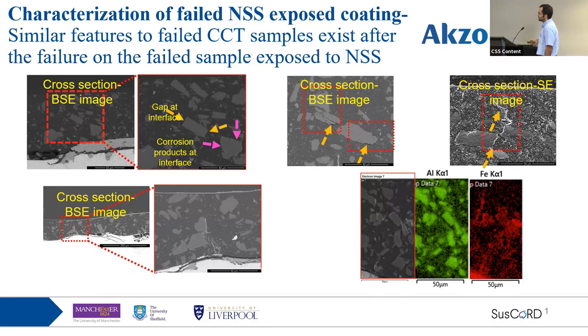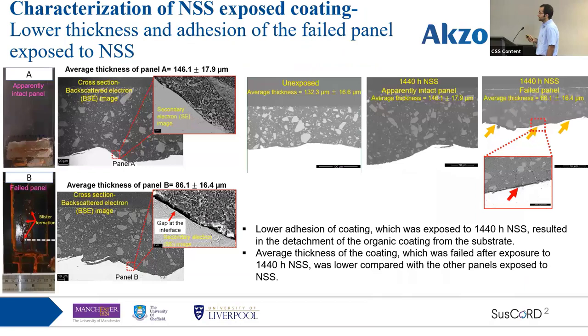But when we looked at the unexposed, apparently intact areas, we couldn't see any crack formations on the samples that were exposed to the neutral salt spray test. So in order to find out why this panel has failed, we started comparing this panel with the panels that didn't show any signs of failure. The first thing that we observed is that the thickness of the panel that failed is significantly lower compared to the other panels.